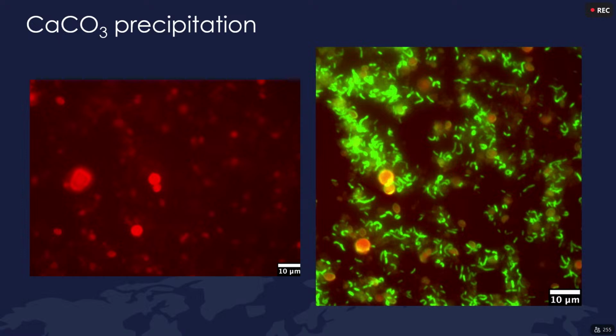So this is just an image of the particles after about 8 hours. And you can see the microbes in green. And what we want to look at here is the fact that these particles are forming outside the cells, which is exactly what we want, right? If you're growing these inside the cells, eventually you'll reach a maximum where the cell dies. And so you have an upper limit to how big you can make these.